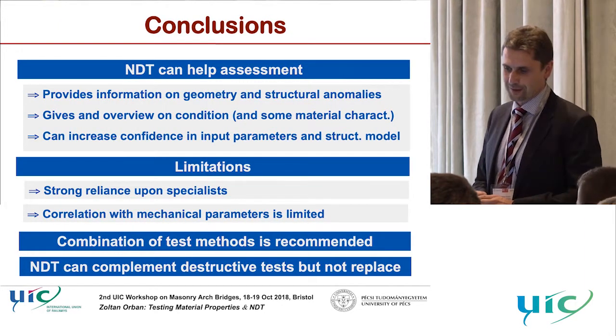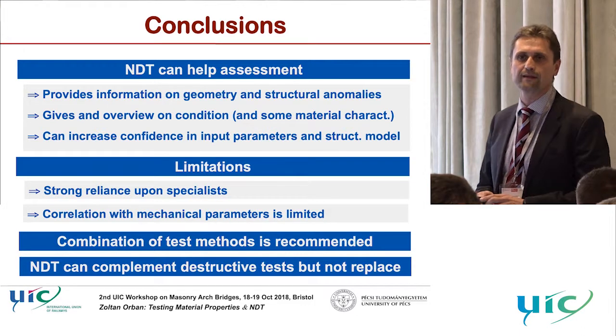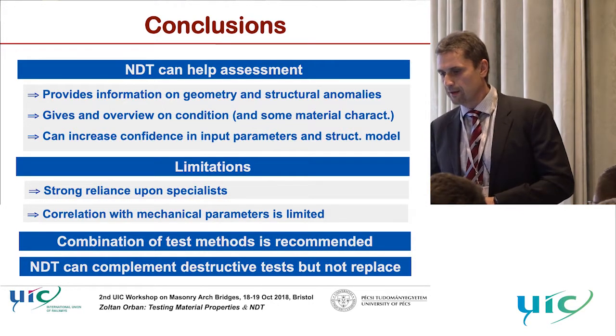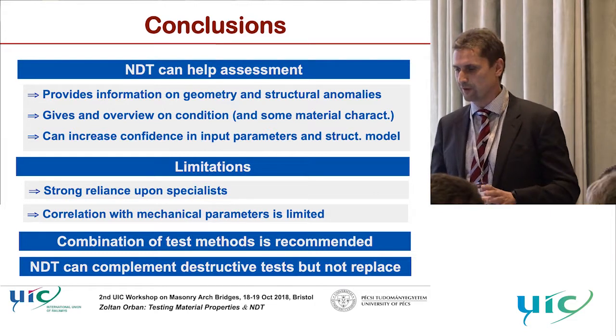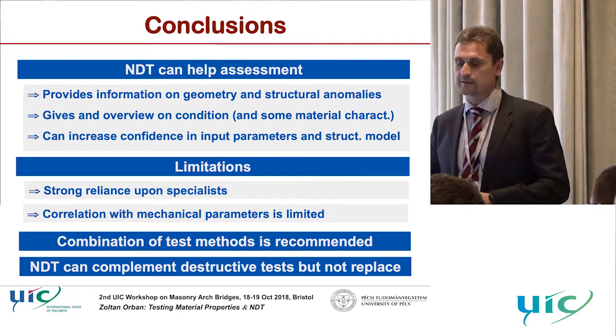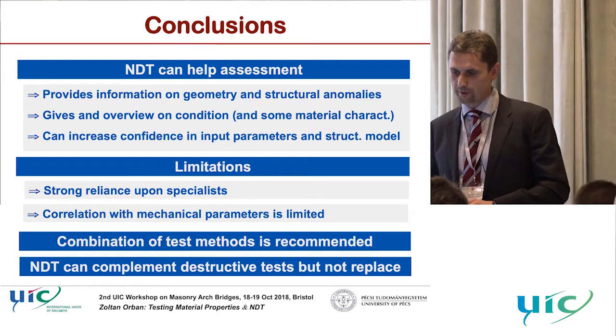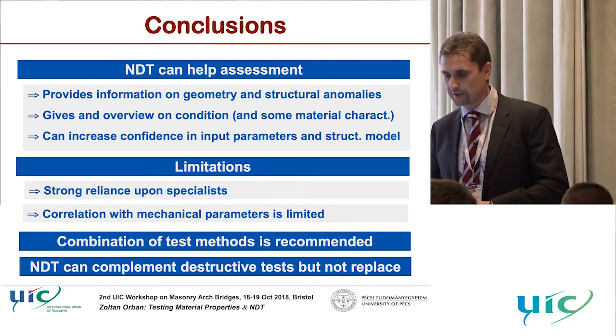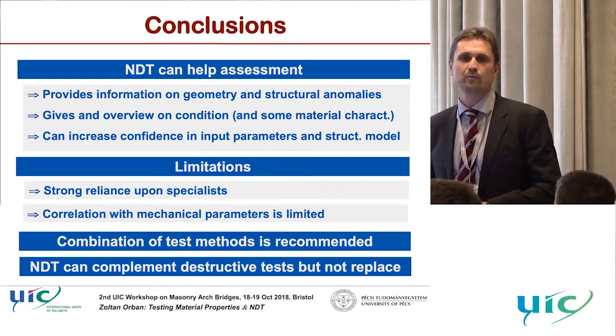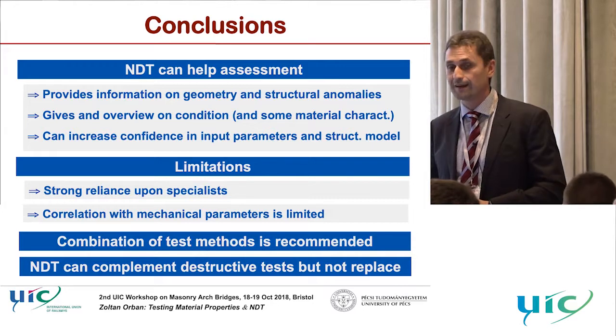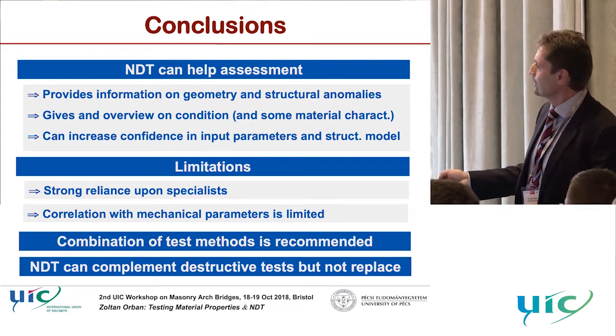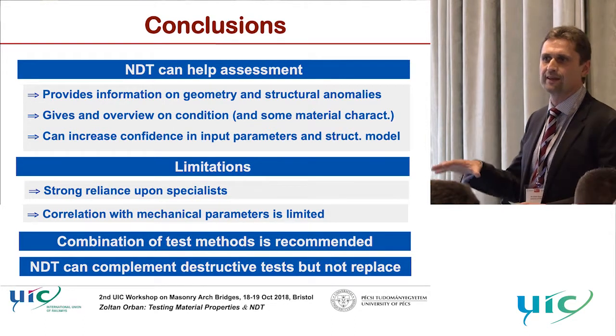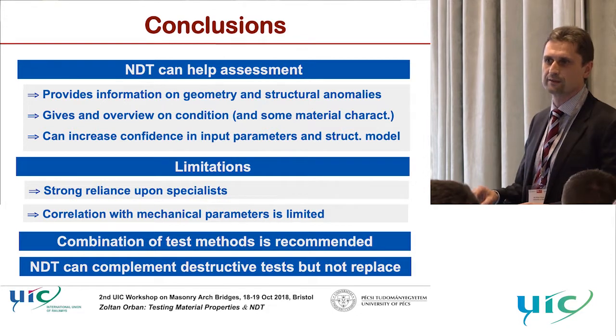In conclusion, I hope I managed to demonstrate that non-destructive testing can help the assessment of arch bridges, providing information on geometry and structural anomalies, an overview of conditions, and in some situations material parameters. It can increase confidence in input parameters for a structural model. However, limitations remain: there is a strong reliance on specialists, and correlation with mechanical parameters is still limited. Therefore a combination of test methods is recommended, and NDT can complement but not yet replace destructive tests. First, a sensitivity analysis on the parameters should be made to define the test program accordingly.